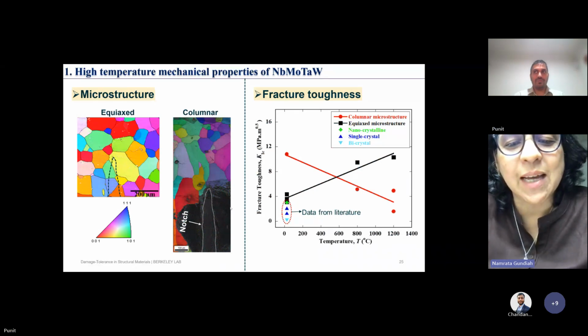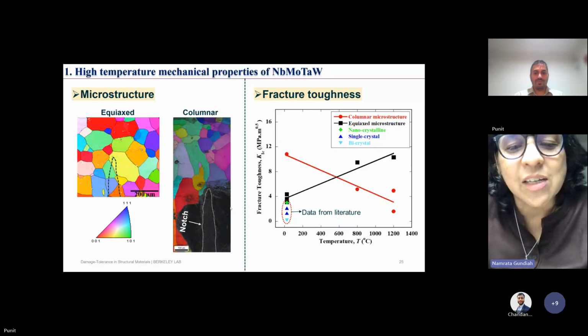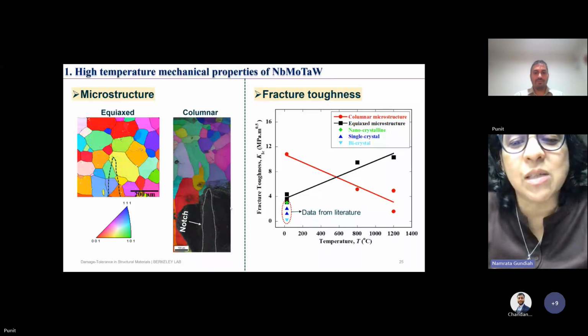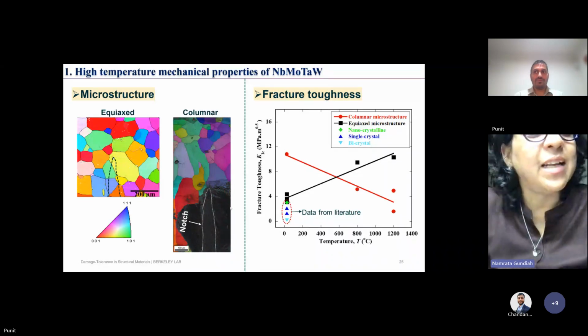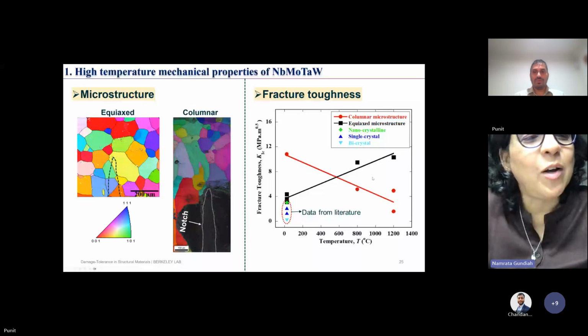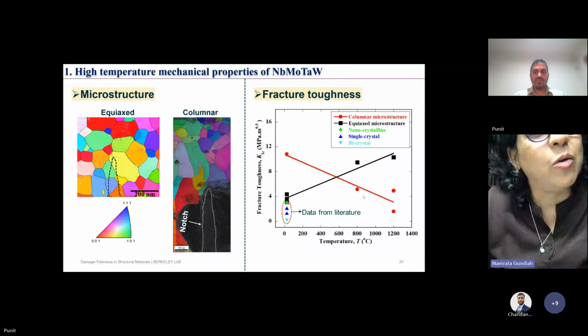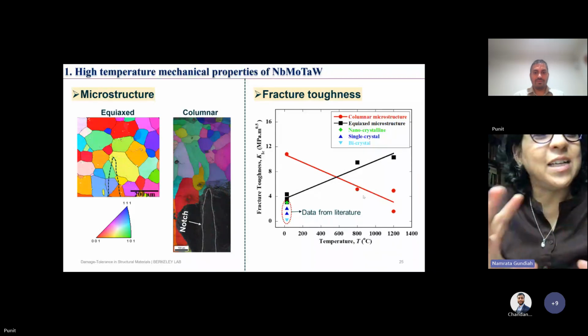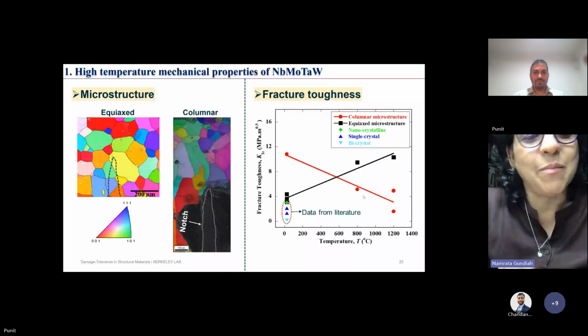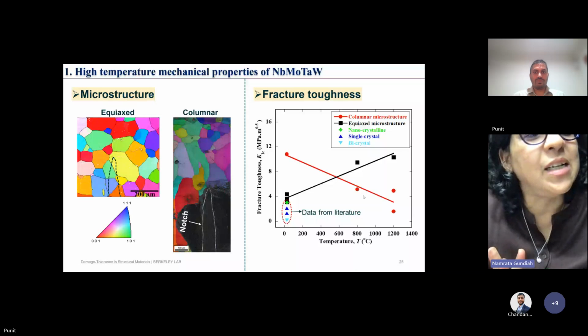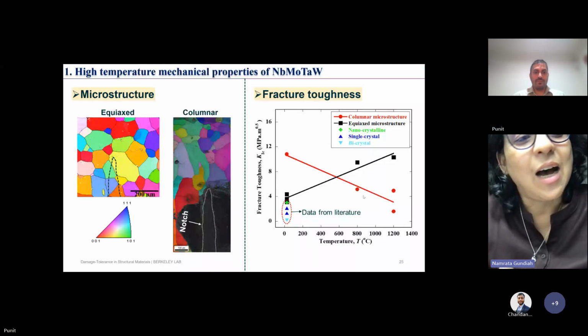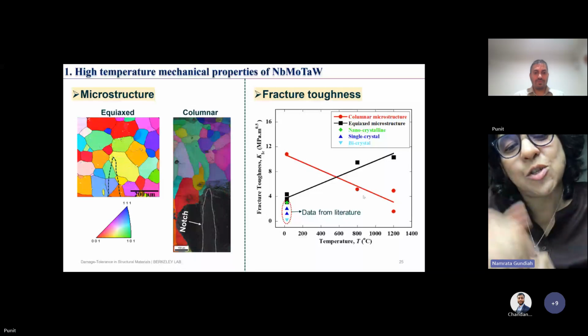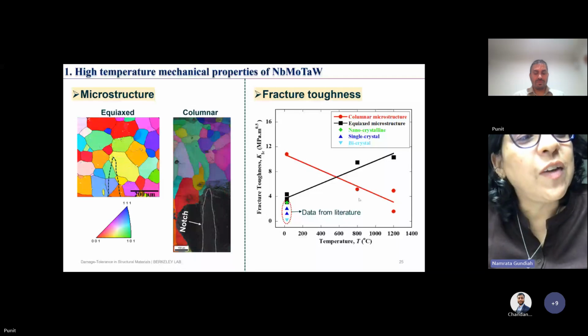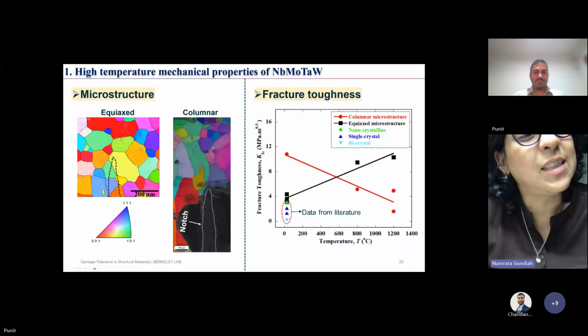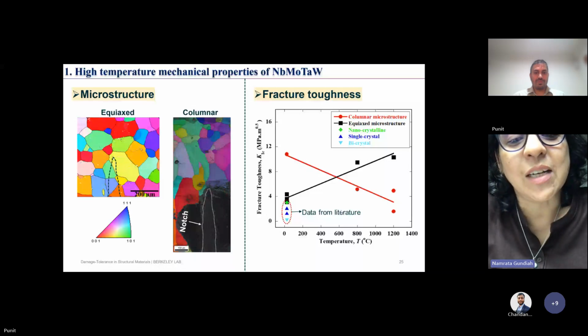And you probably kept it for some amount of time. So there looks like there's a lot of variance in your data at 1200, and there's not much difference between 1200 and 800, although you draw this line like so. Do you want to comment on what the role is? And you also showed these lovely TEM data, these very nice videos of how those structures changed at high temperature. So what do you think is the role of equilibrating the material over longer time durations? So let's say time is a factor. How much of a role do you think the changes you're showing, this very sharp curve, play? Do you think that the variance could become even more different at these temperatures? So you might not find much change between room temperature and high temperatures.